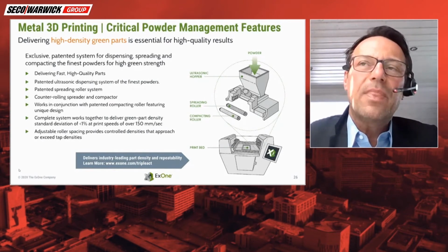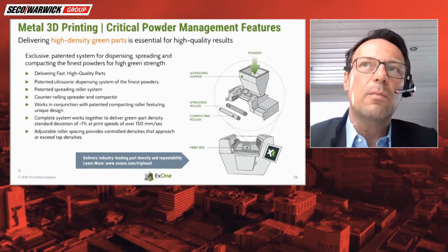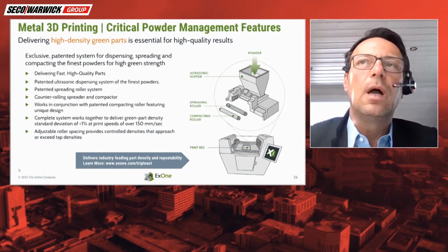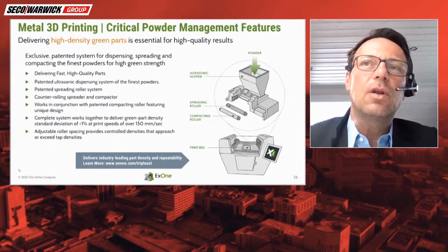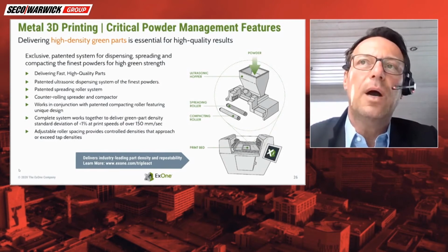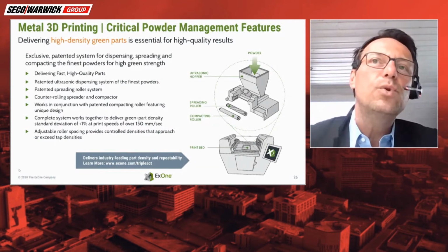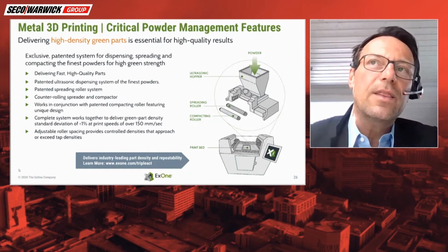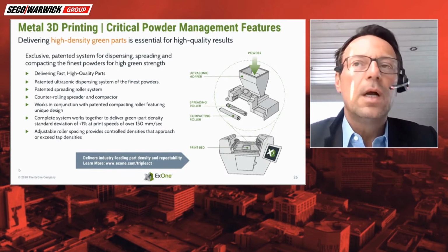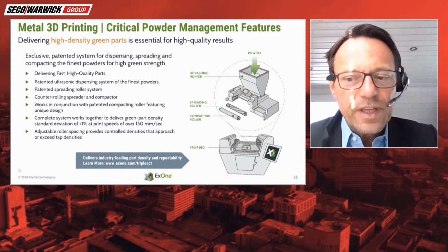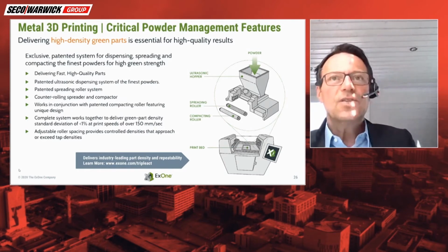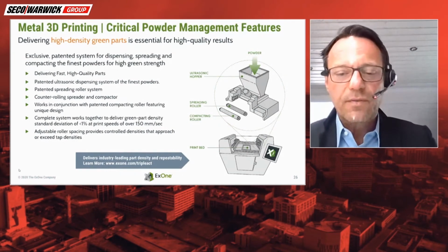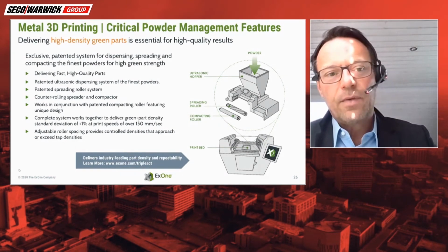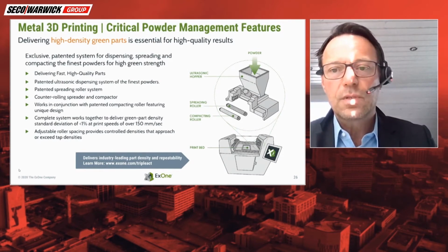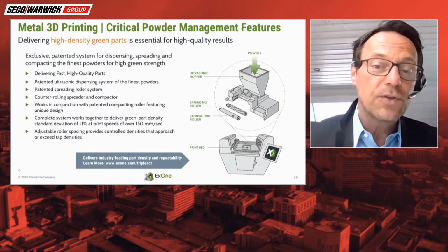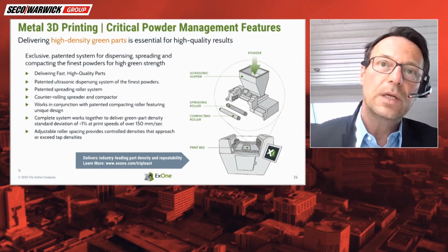And as it comes, physically, fine powders tend to stick together. The particles are sticking together. They are no longer that flowable. And therefore, we have invented this kind of technology, which enables us to recoat even very fine powders. So we have an ultrasonic hopper, a spreading roller and a compacting roller. This combination of ultrasonic hopper and the two rollers gives us the possibility to recoat even a very fine powder. And this is of importance if you want to decrease the cost of the powder in the future, because MIM powders are available, as the MIM companies, metal injection molding companies, use them very often, and tons of that material, so we can use the same powders with our technology.